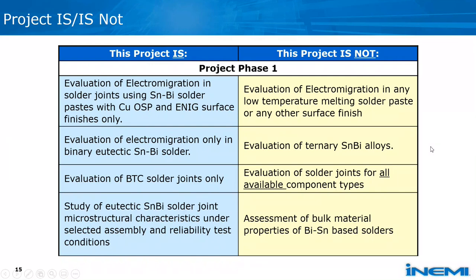Solder joints akin to bottom termination components such as QFNs will be studied. These joints are in the 50 to 150 micron thickness range, which is much less than that for BGA solder joints, and apparently are more at risk for electromigration than the BGA joints. Other solder joints, such as chip components or leaded components, such as QFPs, SOICs, will not be evaluated.